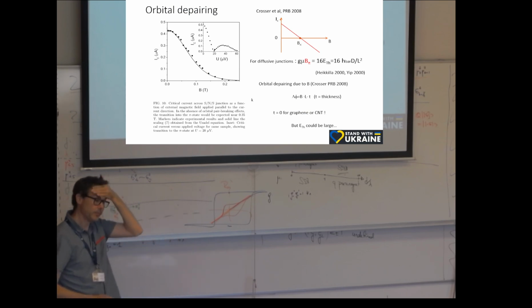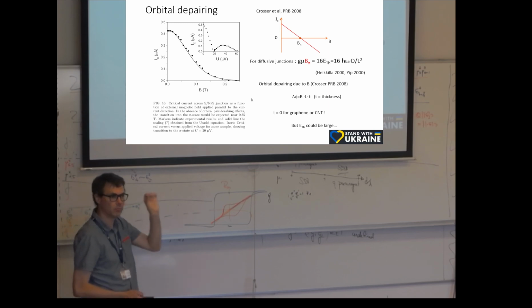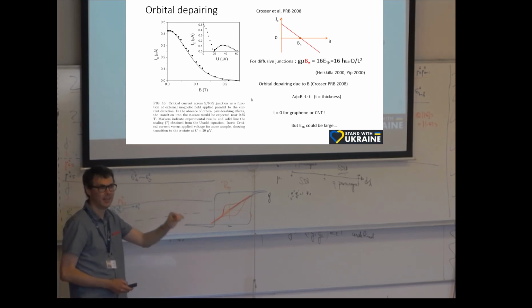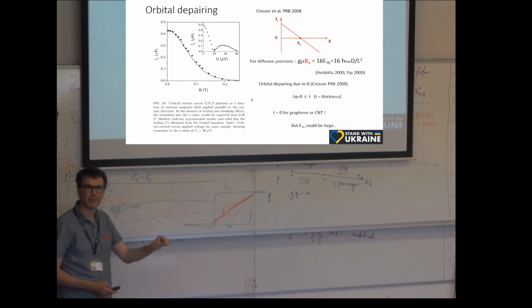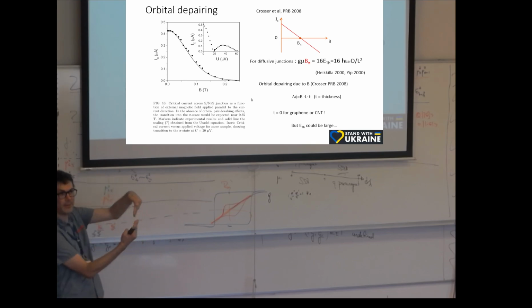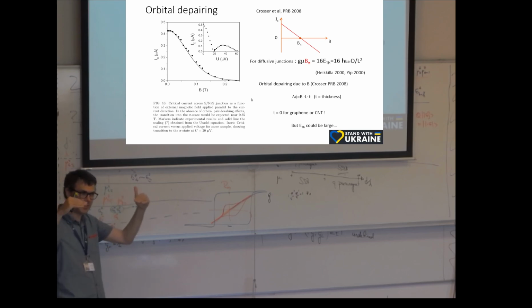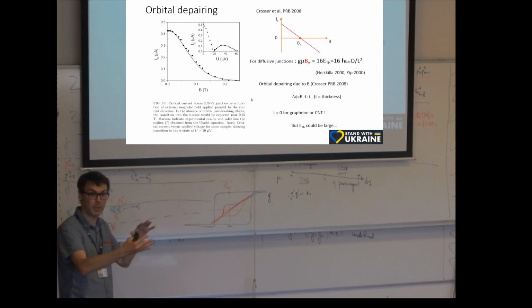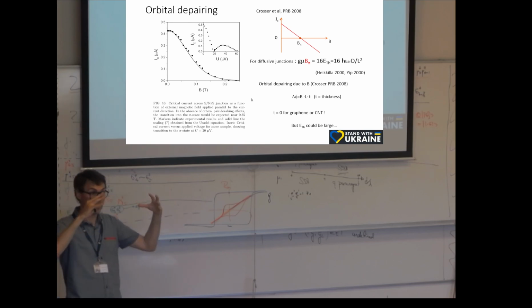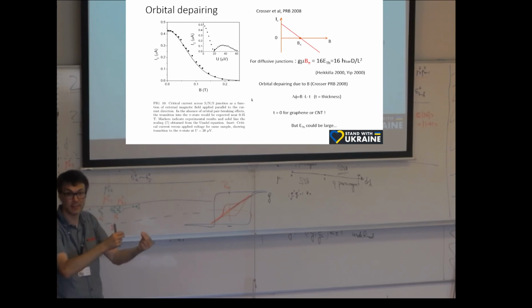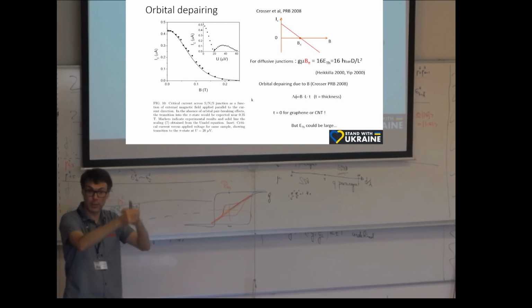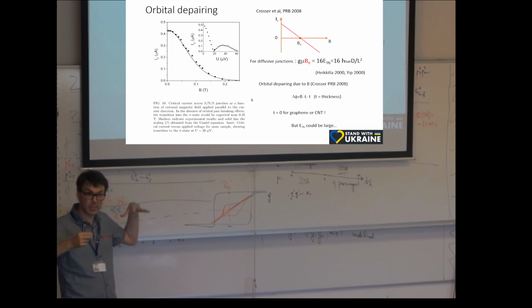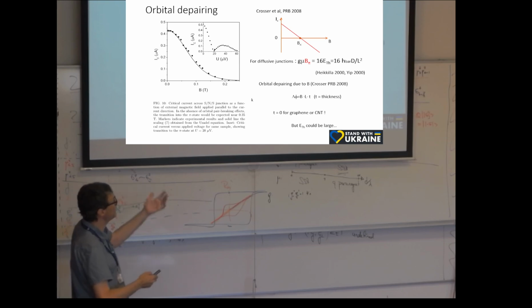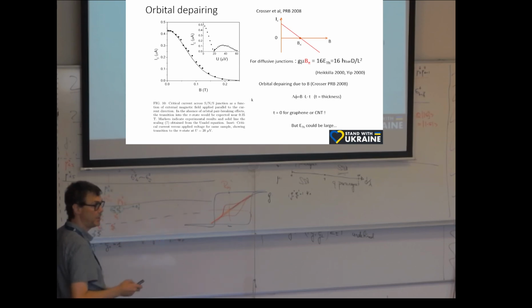Except there is a problem with this idea, and it's that superconductors and Cooper pairs and wave functions really dislike magnetic fields, in many ways, right? So first of all, this effect already is bad for superconductivity, splitting bands, and you have to be at the same momentum, so same energy, so momentum starts to drift away. That's bad. On top of that, there's orbital depairing, which is because you put flux through the superconductor, and it dephases Cooper pairs, because as they fly around the two electrons of the Cooper pair, they pick up different phase because there's flux going through. So that's called orbital depairing, due to motion of electrons in the material.